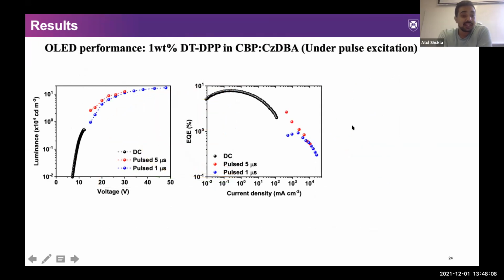So we tried two pulse widths, basically 5 microseconds and 1 microsecond. At initial lower voltages, we found that the 5 microsecond pulse has slightly better performance, but this tends to become similar to the 1 microsecond pulse width results.